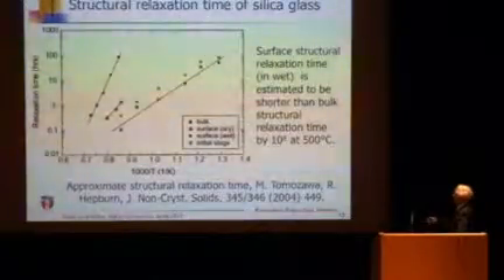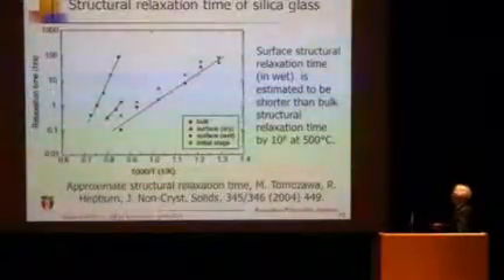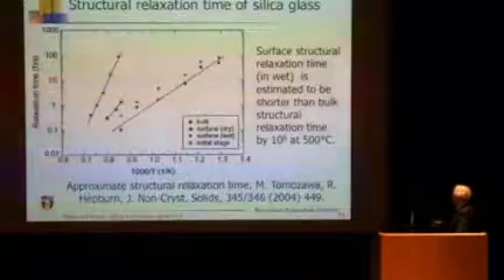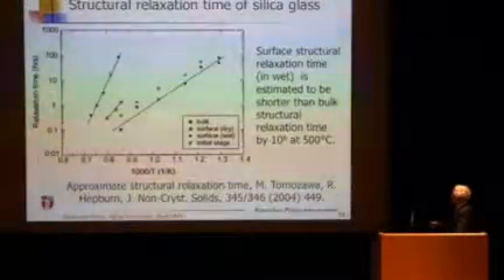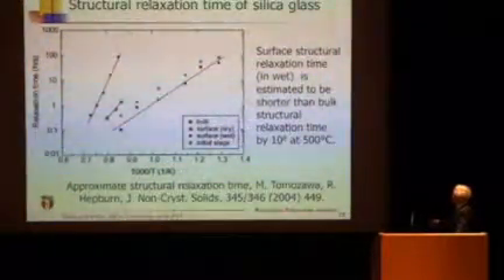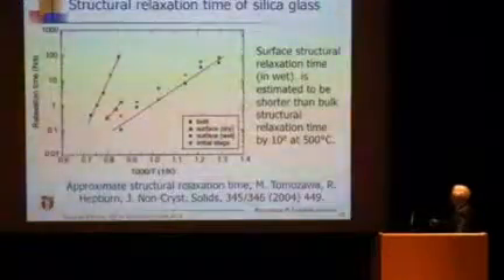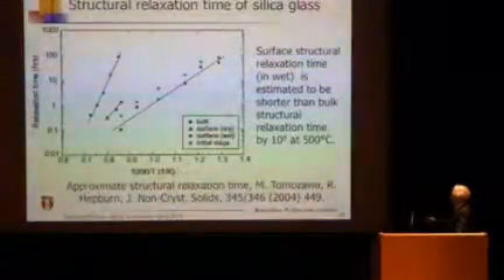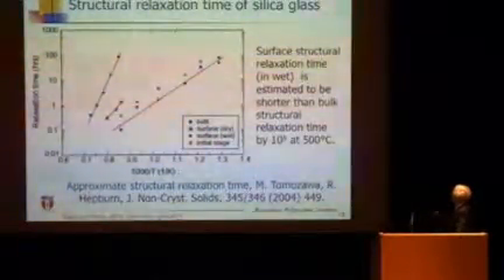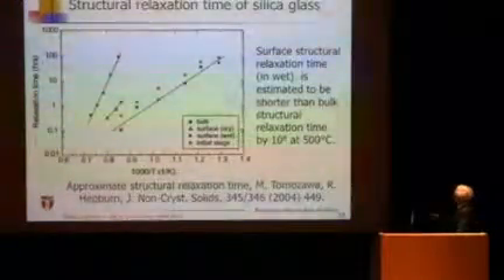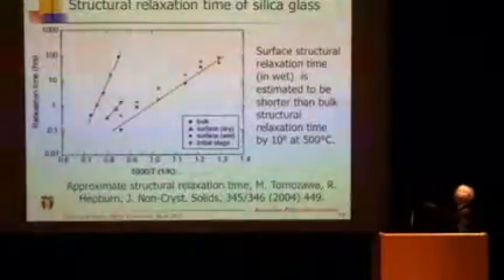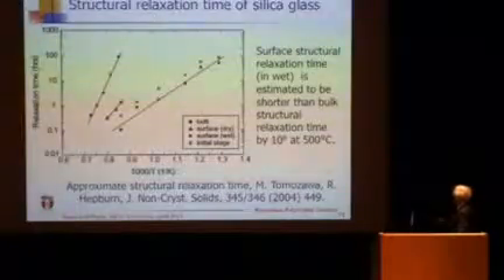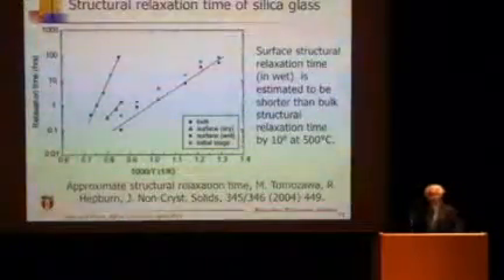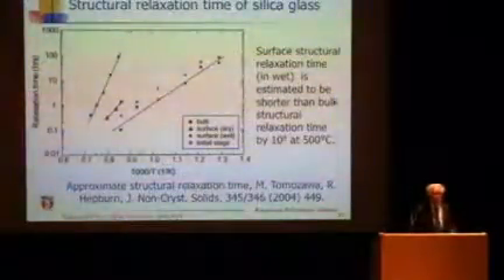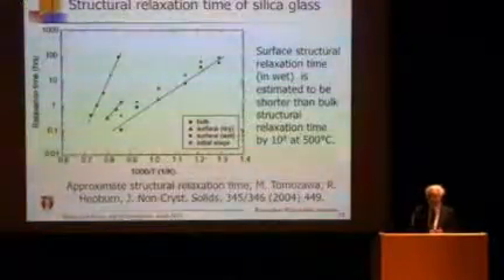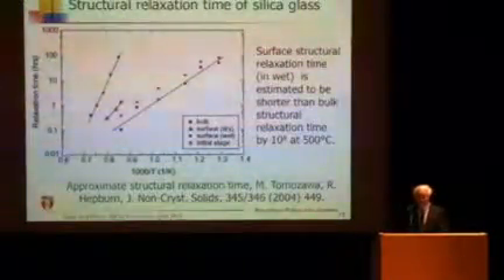Bulk relaxation time changes in this manner. The surface layer changes much faster, with a smaller relaxation time. And when you make it dry, it's a little bit longer, but far lower than bulk. If you extrapolate to 500 degrees around here, and extrapolate this one, the relaxation time difference is 10 to the 8. Eight orders of magnitude faster relaxation at the surface when there's moisture around.